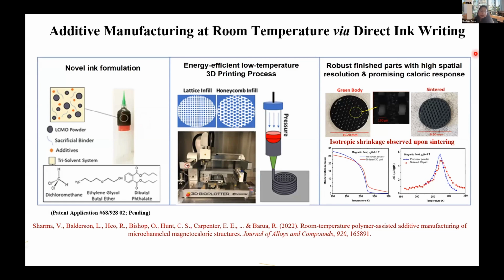Direct ink writing is essentially a three-step process where, instead of starting with powder, we start with an ink. Our starting material is an LCMO powder combined with a sacrificial binder, additives, and a tri-solvent system to make an ink that flows nicely.